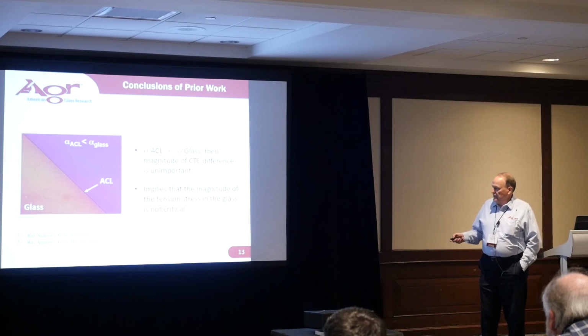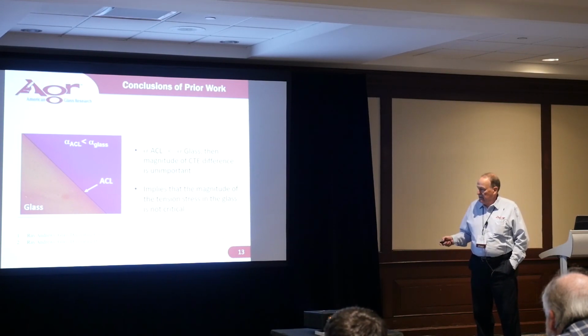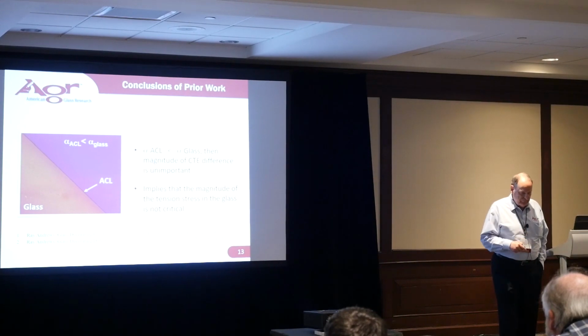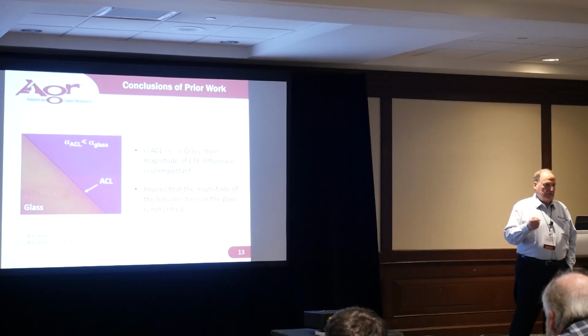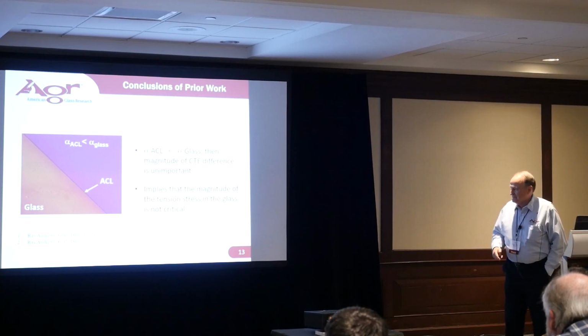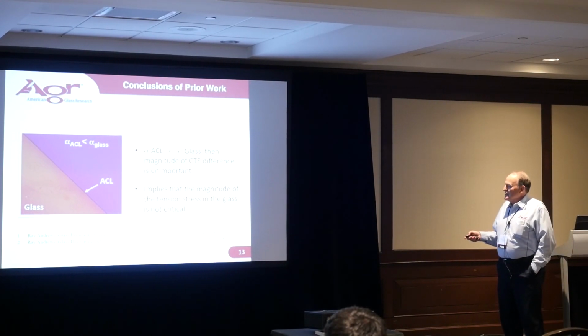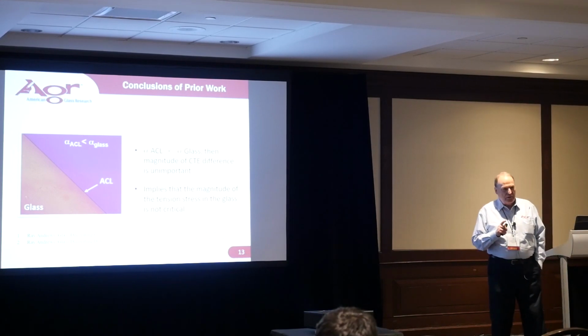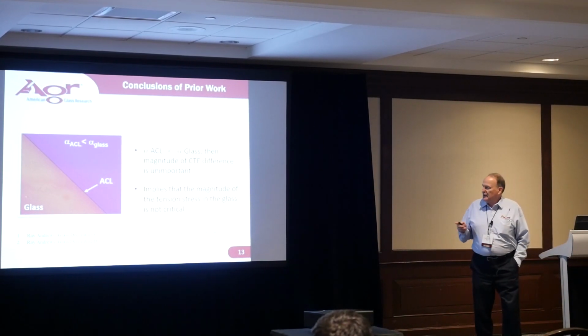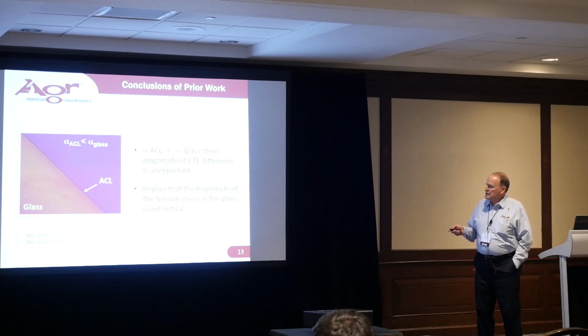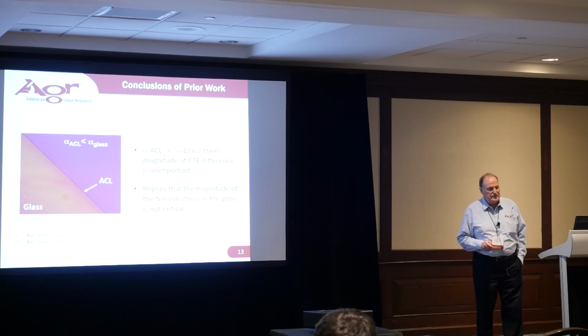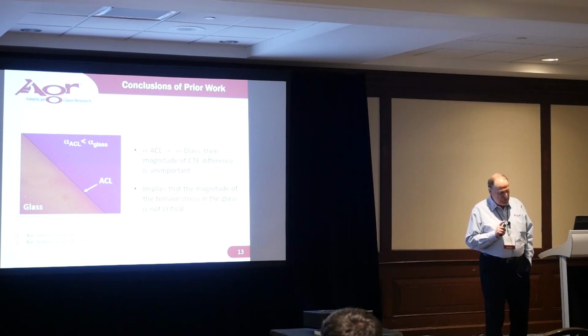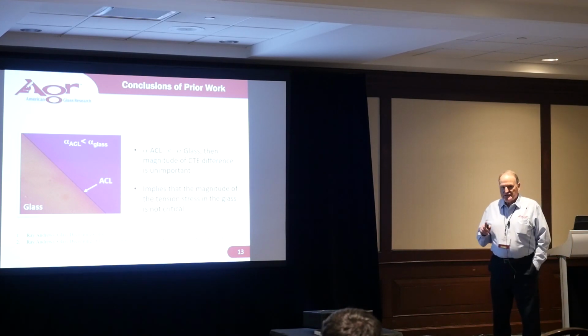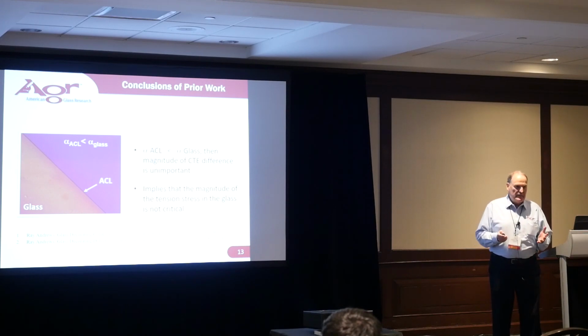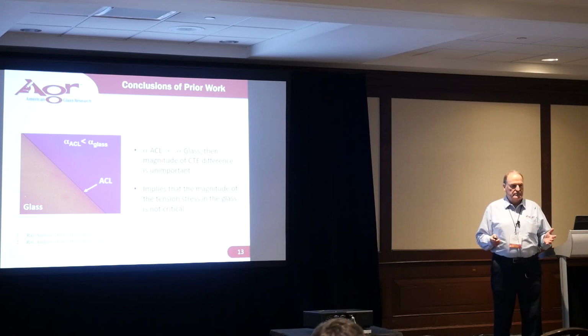We found a couple of references. There are many others, but here's two by Ray Andrews, formerly of the Drakenfeld, which became Ferro, which, whatever. In his writings, as well as with other people, they talked about this situation of the coefficient of expansion of the ACL being less than the glass. And the comment was almost universally made that if that's the direction you go, if that's the kind of mismatch you have, then the magnitude of that mismatch doesn't matter.